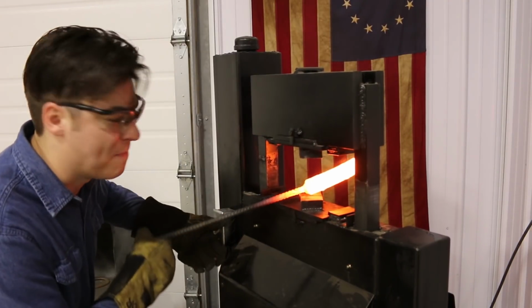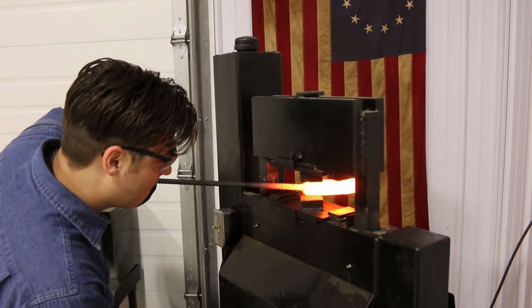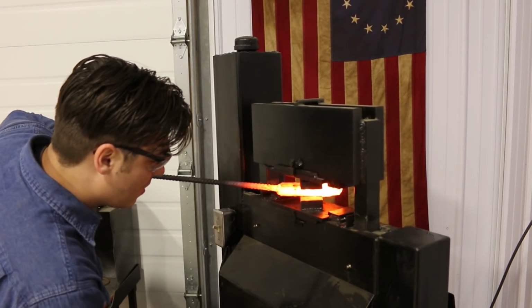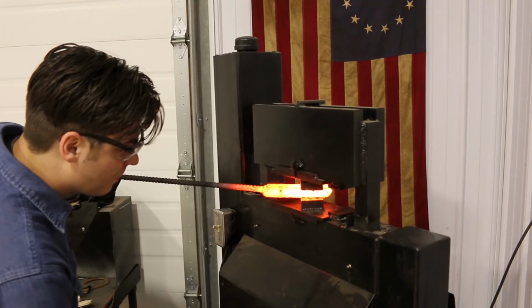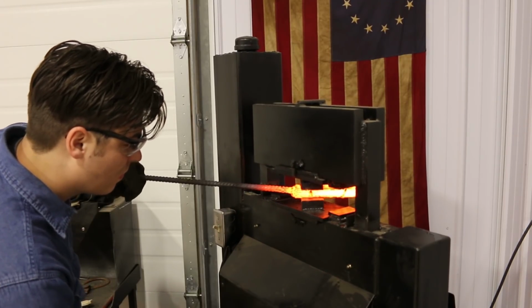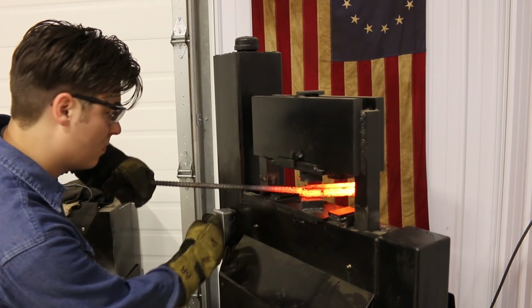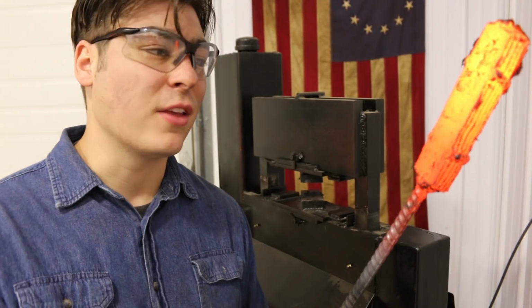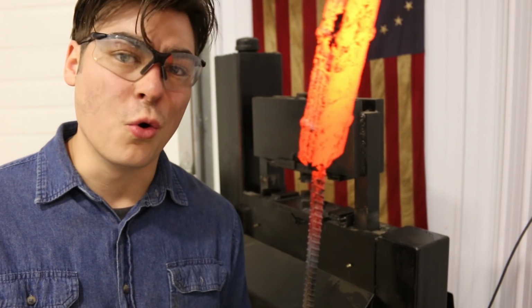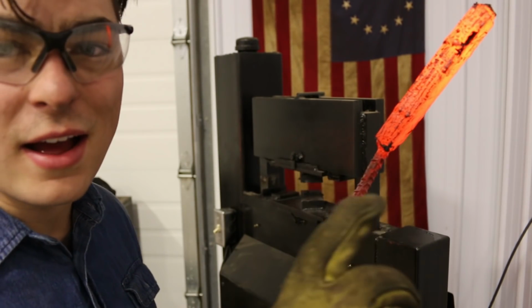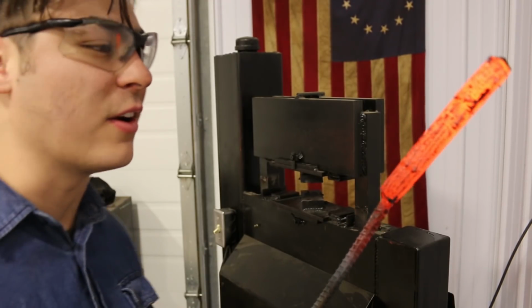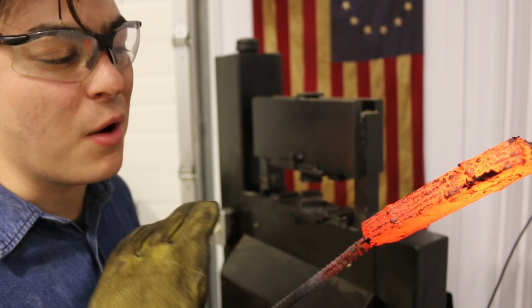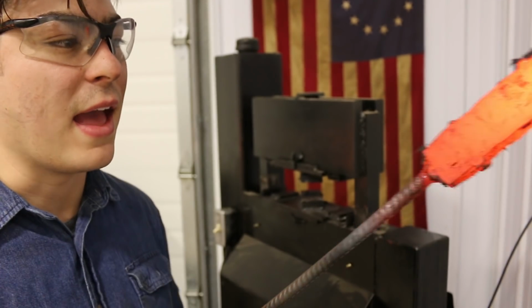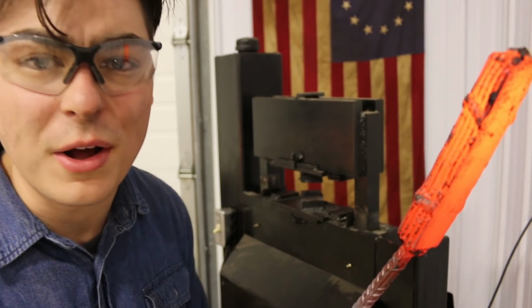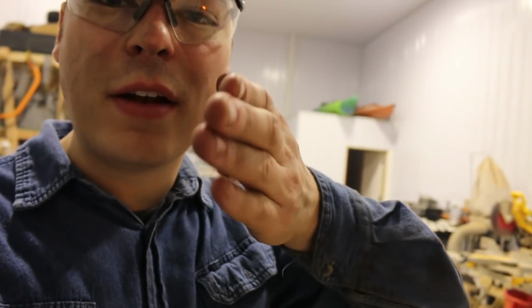All right, we're gonna press this one more time. A good way to tell if your forge weld is stuck is to watch it cool. So if you can see the layers cooling inconsistently, you know that they are not stuck together. But this is one homogeneous piece now. You can see that it's losing its color altogether, and that's a real good sign. That means that we have a good forge weld. I'm gonna hit it 1 or 2 more times just to make sure it's all nice and flat and even before I flip it and start hitting from the other side.